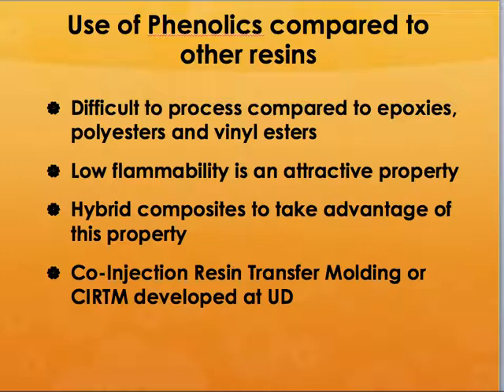So in order to get good properties, because it is difficult to process, you have a method that was developed by the Center for Composite Materials at University of Delaware and the Army Research Lab at Aberdeen. They came up with a technique called co-injection resin transfer molding. You co-inject the resin system into a preform. So the bottom would be the vinyl ester and the top would be the phenolic type of resin system. So the processing is not that difficult, and any byproducts that come out can easily be removed from the composite system.